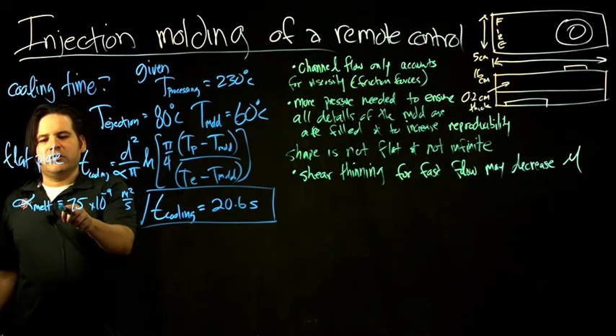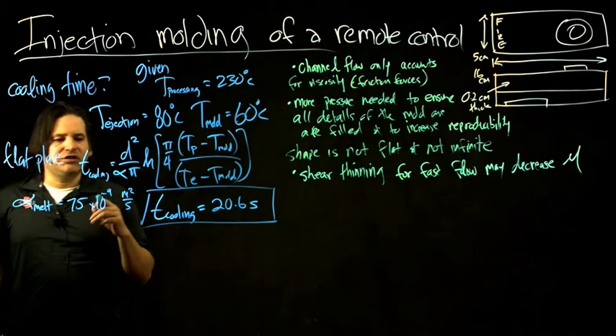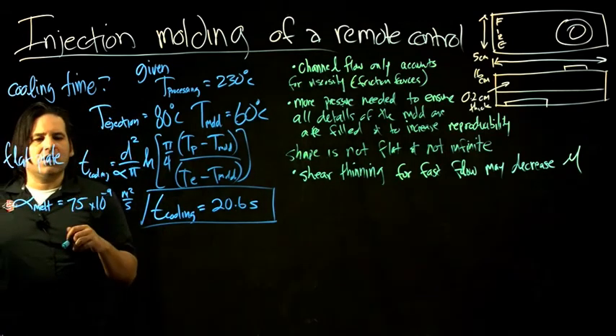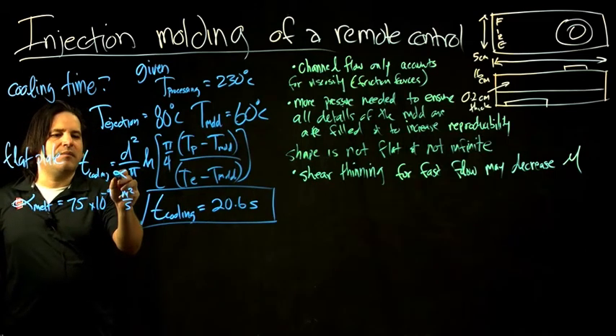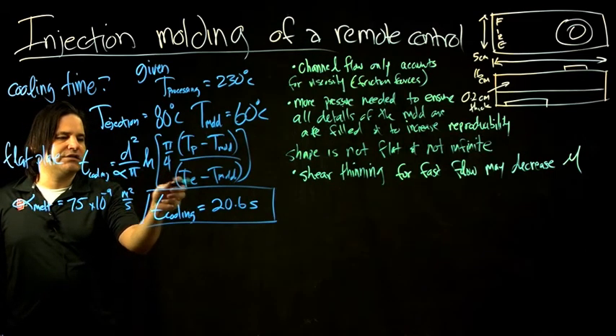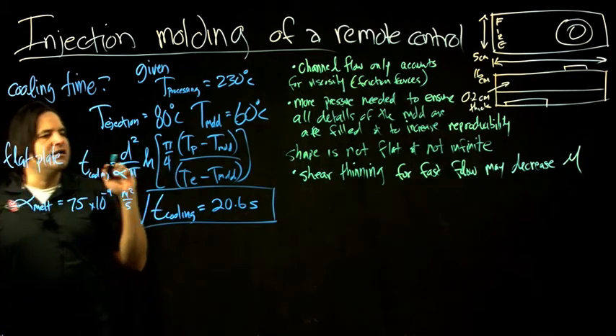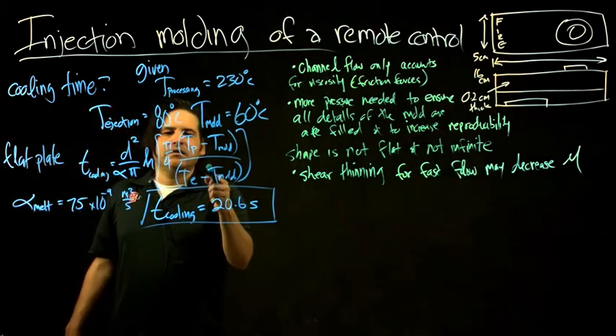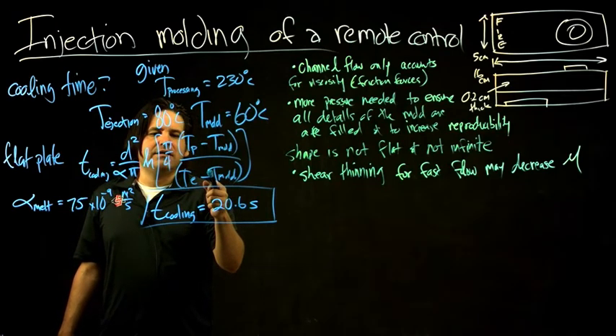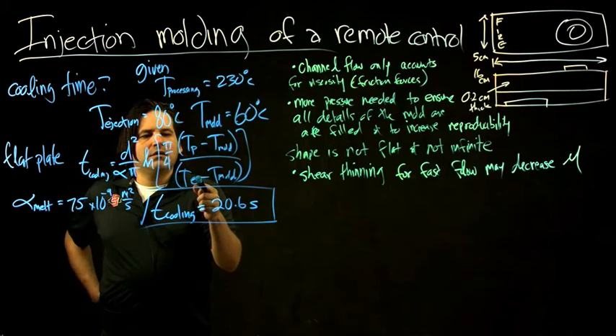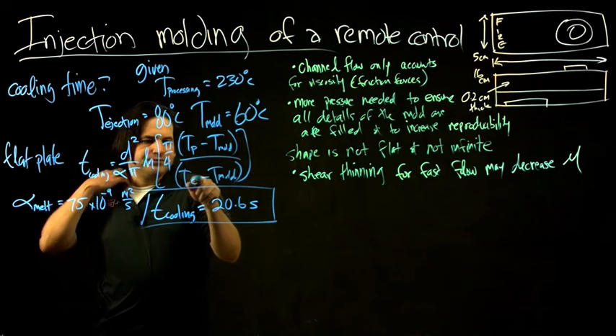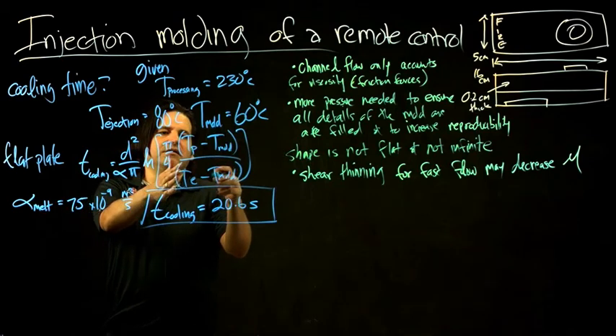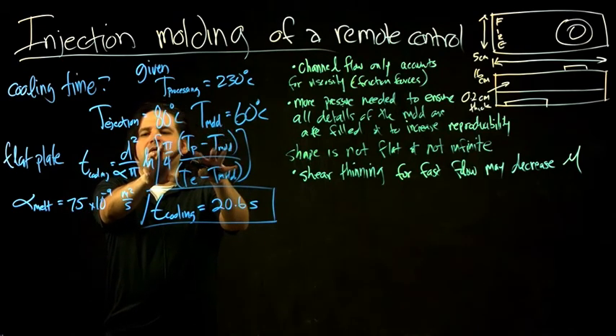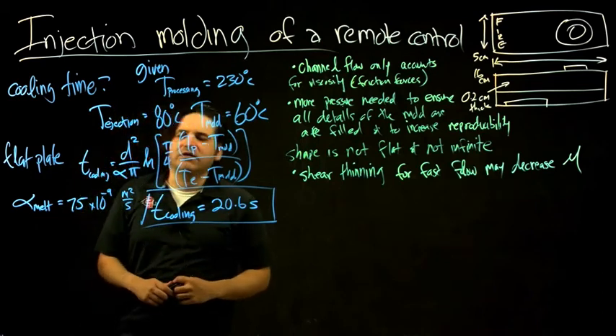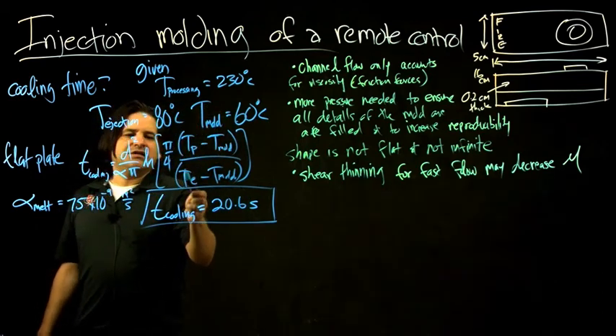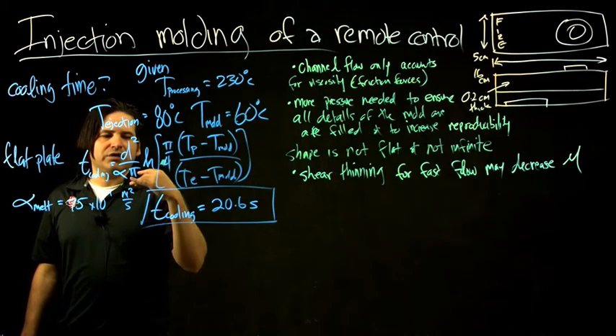In material properties, the thermal diffusivity changes slightly between a liquid and a solid, so it would not necessarily be constant when you're changing phase. And you can play with these parameters here. If you had a larger ejection temperature, you would have a bigger difference here, and that would make this number smaller, and you would have a lower cooling time here. But as we said, if this is too warm, the part might deform when you try to punch it out of the mold.